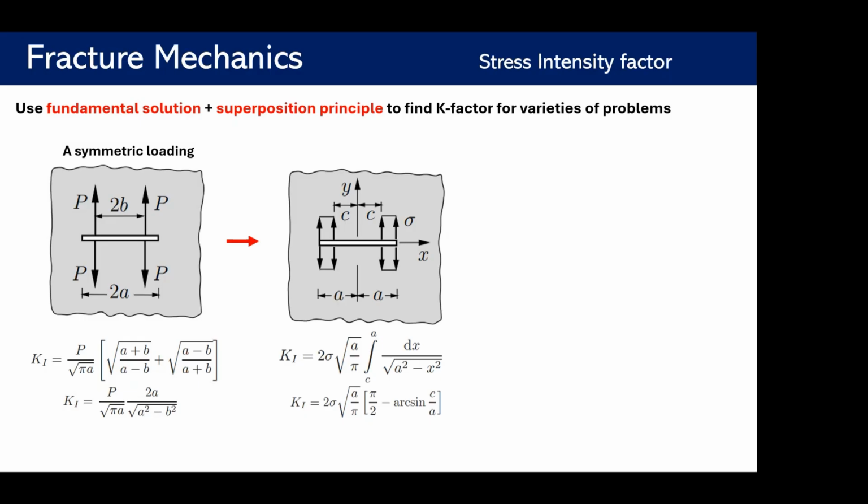You can use the integration. Absolutely, we integrate from this formula here. A is always constant. You always integrate over B. You can assume B as X and integrate over the formula here to find the stress intensity factor for this case.